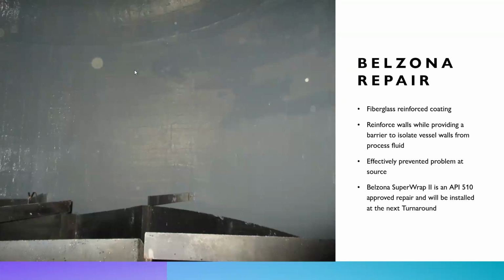In this case, we used a fiberglass instead of a carbon fiber, and we used the liner with the fiberglass. So instead of doing a carbon fiber wrap and then a liner, we embedded the fiberglass with the liner in a one-step process. This was done because this was a lower pressure application, and it was just a little bit easier of an application than the last one, which was a little higher pressure application. So it worked great. We installed it, let it cure, got them back into service.